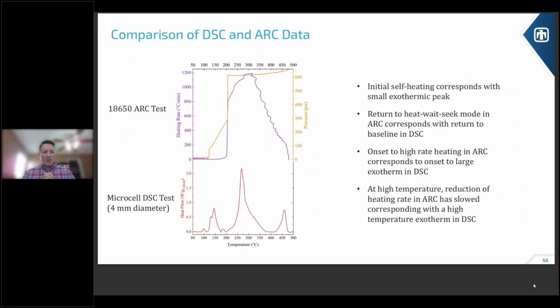So why am I showing you ARC? I'm showing you ARC to compare to the DSC. The top plot is a full 18650 cell. That's the cell that we purchased, we got in our hands, we stuck it in the ARC, and then we ramped up the temperature and looked at the response. The bottom one is only 4 millimeters in diameter. So just very small sample sizes in a calorimeter.